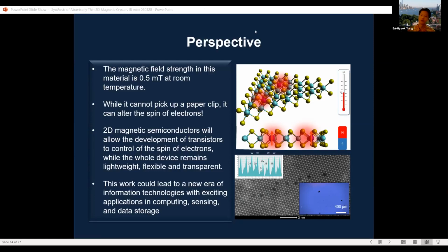With iron doping, you can dope anything, not just iron, but iron is one of the materials that, through theory work, achieves room temperature ferromagnetism. Basically, we make this 2D semiconductor and turn it into a 2D semiconductor with ferromagnetic properties, and that shows at room temperature. It is extremely important because if it shows all the properties but only at cryogenic temperatures, then from a practicality point of view it's useless, right? But we showed for the first time that this is a room temperature material, and we scrutinized it atom by atom and over all the areas. That's what we did.